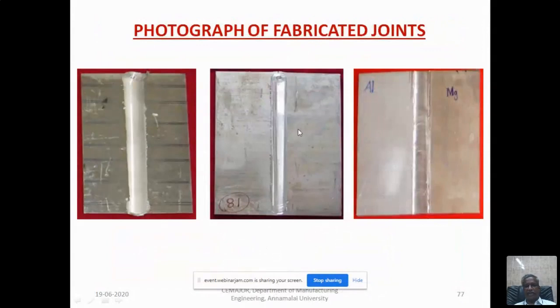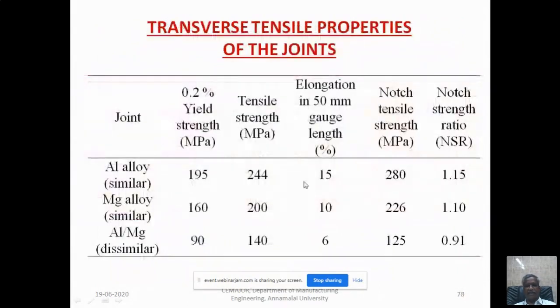And we welded aluminum with aluminum, magnesium with magnesium, and the second one, aluminum and magnesium, all joints made using this process. And this is the comparison. For the aluminum similar joint, we got 244 megapascal tensile strength, and for the magnesium alloy 200 megapascal. And for dissimilar, we got 140. Even that is good, because you will not get this much strength in any process other than friction welding.